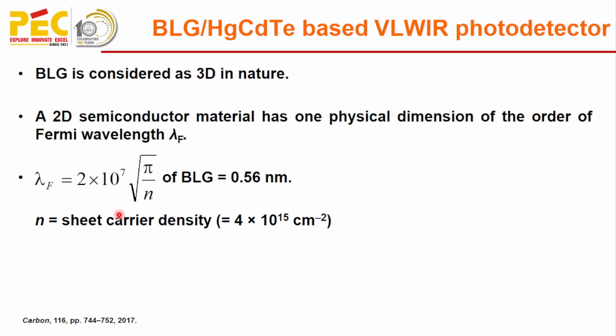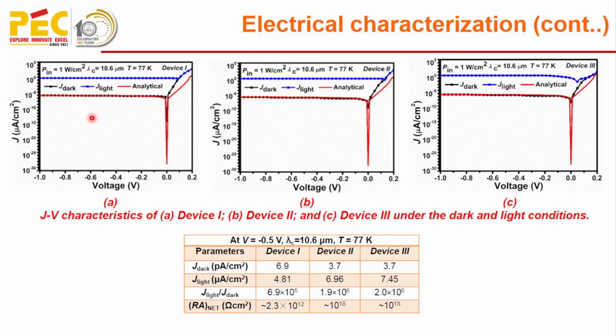So here I have plotted the graph between the current density and the voltage under dark and illumination conditions, and all the results are verified with the analytical modeling based on drift diffusion, tunneling and Chu's model. And it was found that the dark current density perfectly matches in reverse bias with the analytical modeling, and the dark current density will increase with the biasing voltage. So we can see here that this is our current density at a voltage of minus 0.5 volt with a wavelength of 10.6 micrometer, which is the cutoff wavelength, and at a temperature of 77 Kelvin.